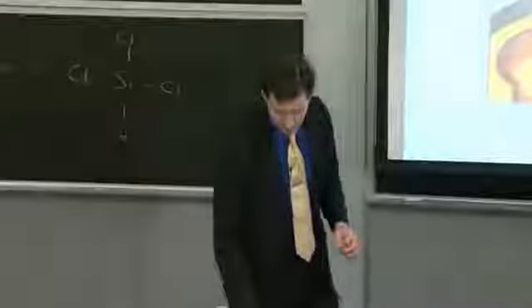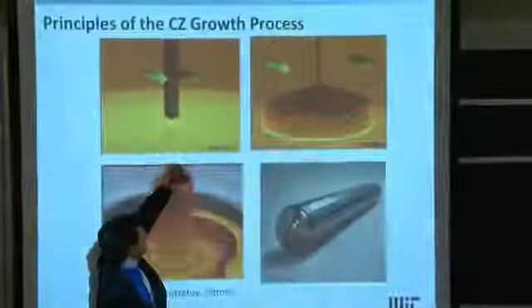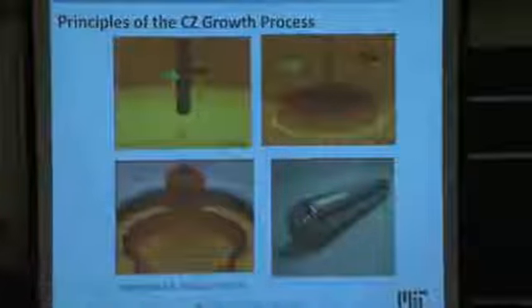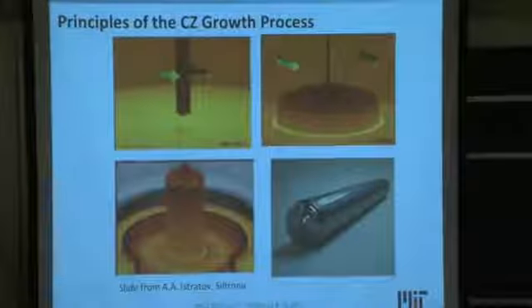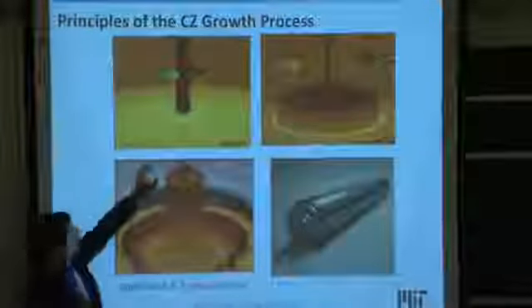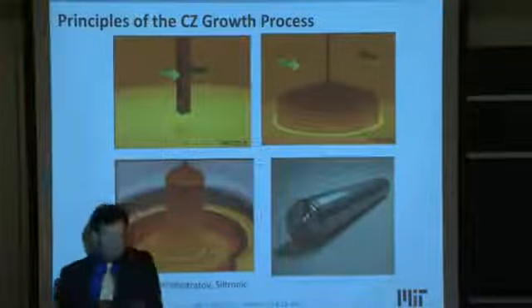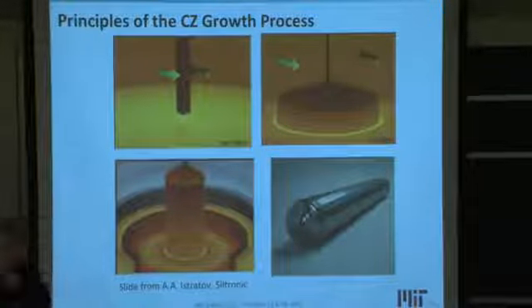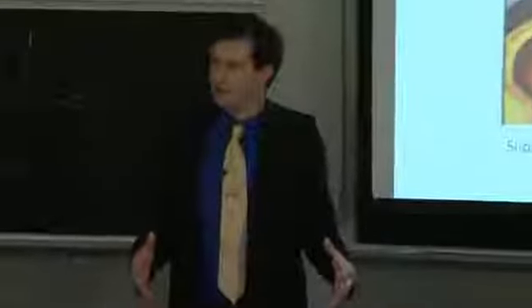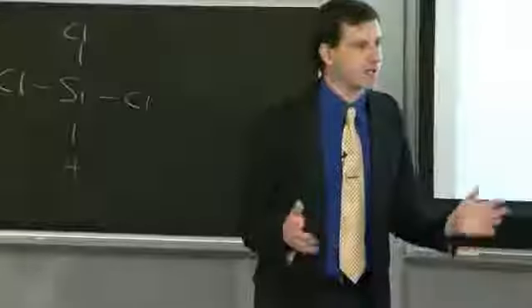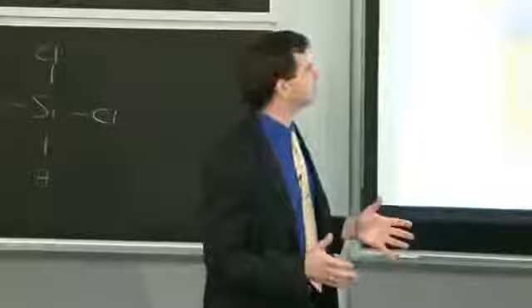So the seed is a single crystalline material. And what ends up happening is, as you introduce the seed into the material and begin pulling, you start pulling out this single crystalline crystal. It's a thing of beauty. And this seed is actually very, very narrow in diameter. It might be about that big around. And it's able to support this ingot of usually a few tens to hundreds of kilograms in mass underneath it. That's because silicon is very strong, even though it's brittle.